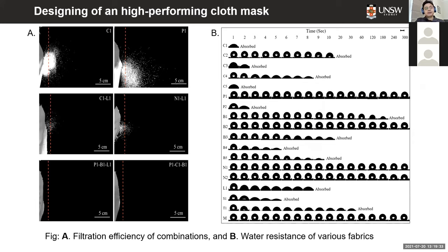Figure A shows a few representative images of the droplet blocking capability of a single layer face mask, two layer face mask, and three layer face mask. We found that increasing the number of layers significantly increases the droplet blocking efficiency, on average by 20 times per additional fabric layer. We also checked the water resistance capacity of the fabrics, which is very important for determining